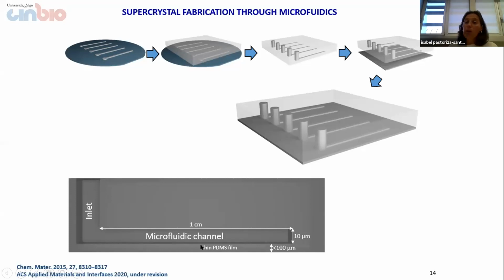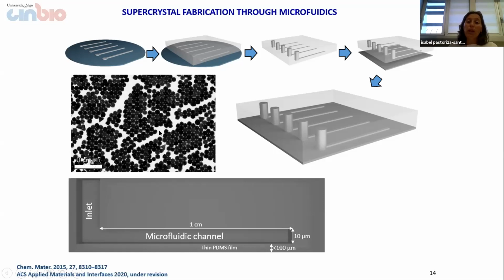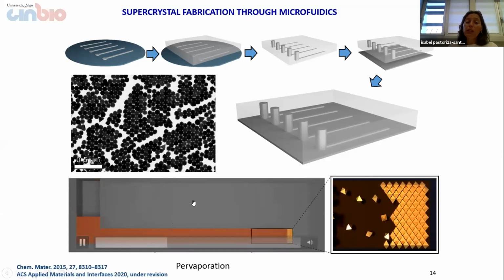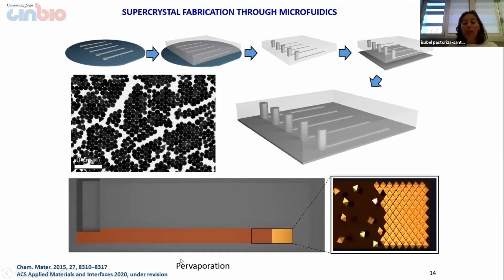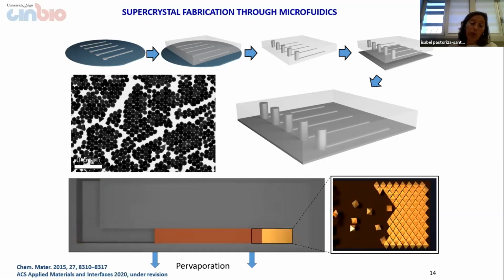That is fundamental to induce the assembly of the nanoparticles, because the next step is to take the gold octahedra. These nanoparticles are 75 nanometers in side length, and we prepare a very concentrated colloidal dispersion with the right concentration of the surfactant. This is a very important point. And using a pump, we just inject it into the microchannel, and this will produce the evaporation of the solvent through this PDMS film, and the flow of the nanoparticles to the end of the microchannel, with the nucleation and growth of the supercrystal.